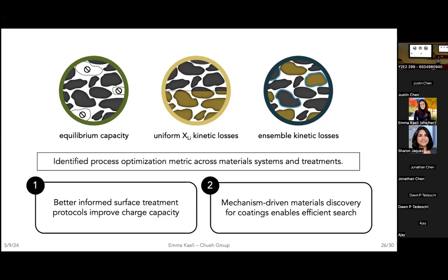Following up on that, what stops you from going to lower and lower voltages to try to recover the shoulder faster? Now, there's a number of things. One is protecting the NMC. You are actually at risk of over-lithiating and causing irreversible reactions. And then additionally, solid electrolyte, not only can it oxidize, but the neutral solid electrolyte, even before you oxidize, can be reduced as well. And so you don't want to go below that reduction potential.